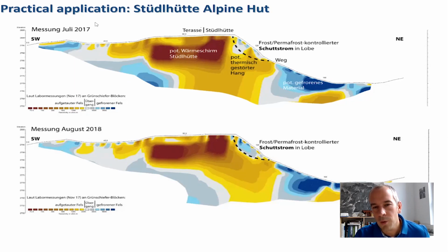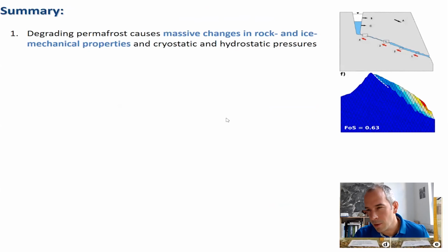So the first thing we recommended to them in 2017 is to divert the water from the roof that was always put into the northern lobe. And by that, we could see simply in 1 year, we also have thermal sensors to show that, that the northern slope started to restabilize a little bit and to get cooler because it had no water penetration coming from above. Okay, let's summarize this.